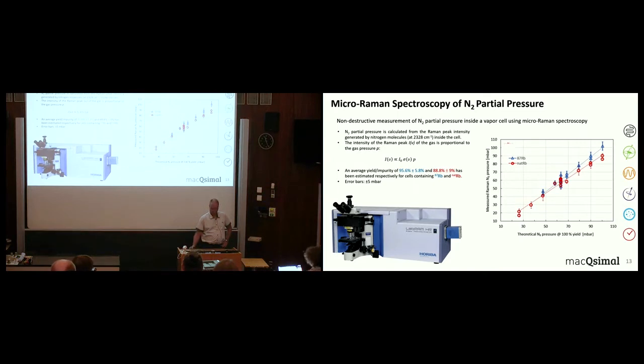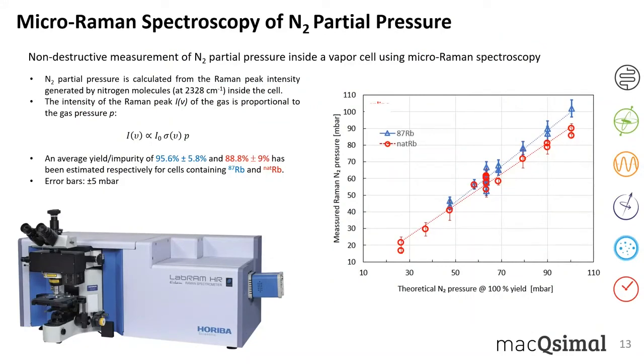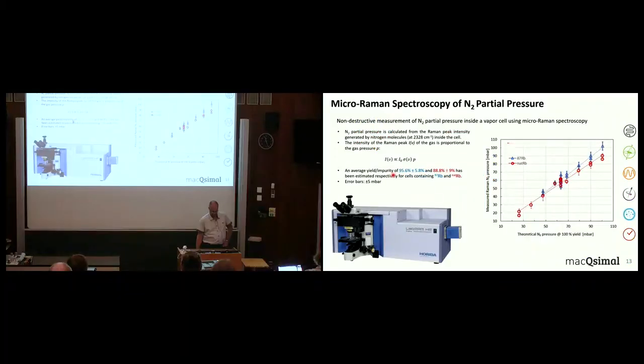So the azide is normally 100% rubidium azide, but there are also some other elements inside from the process to fabricate it, and the decomposition yield is never 100% either. But here we could evaluate that for cells we do with isotopically enriched 87 rubidium, we have an average yield of about 95%. And in the case of natural abundant rubidium azide, we have a yield of about 88%.